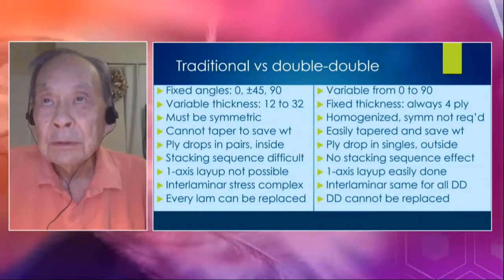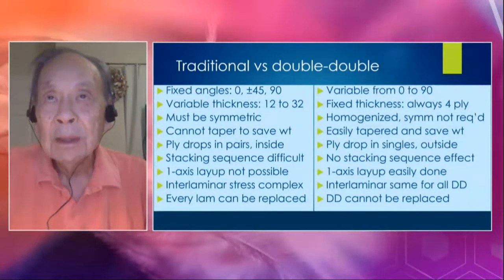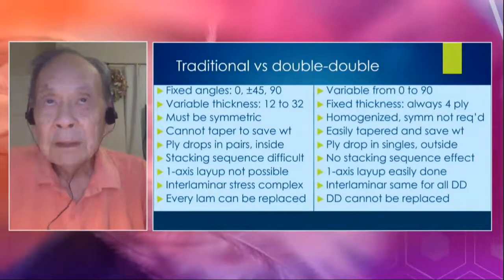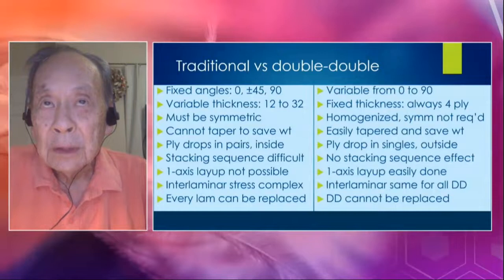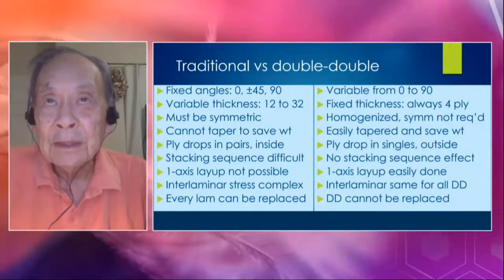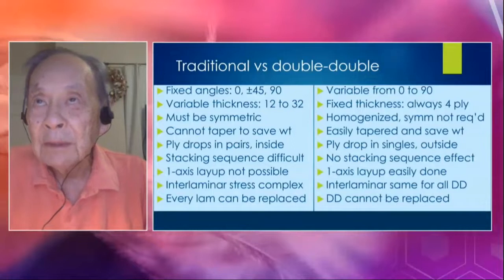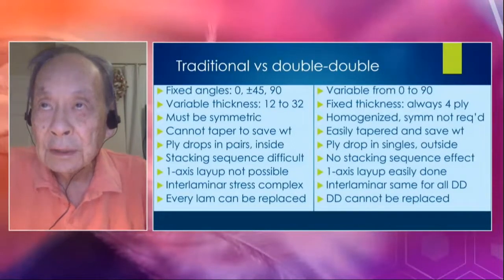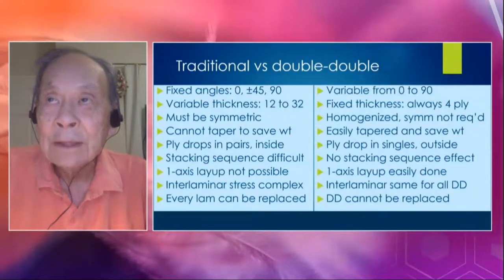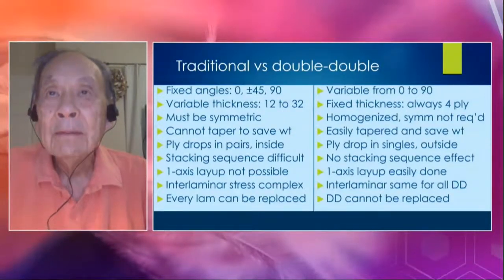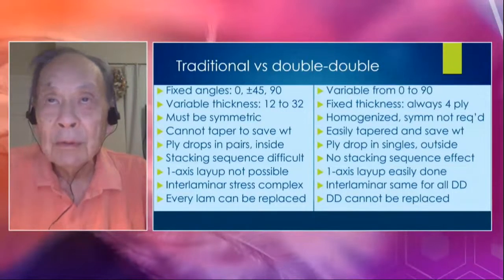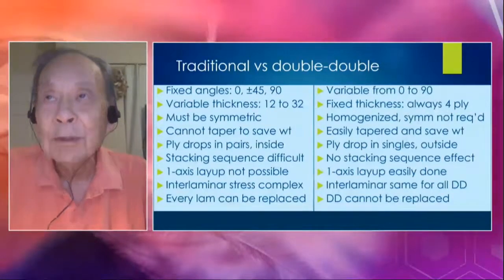And then, of course, you can taper it, because you can reduce the number of repeats from 10 to 9 to 8, whereas the quad you cannot do that. And in terms of ply drops, the traditional way is to have the ply drops inside the laminate, whereas in the double-double, we can have ply drops in singles now instead of symmetric pairs on the outside. And then the stacking sequence is always a problem with quad, but there's no stacking sequence effects because there are only 2 possible stacking sequences, so the issue goes away.